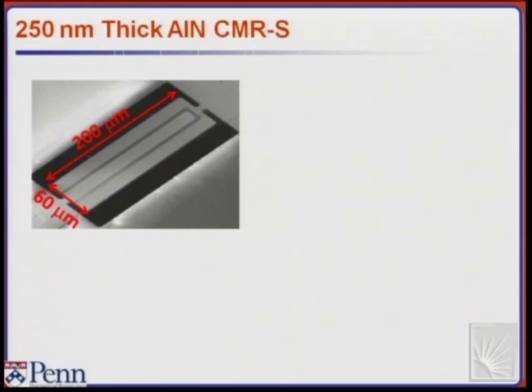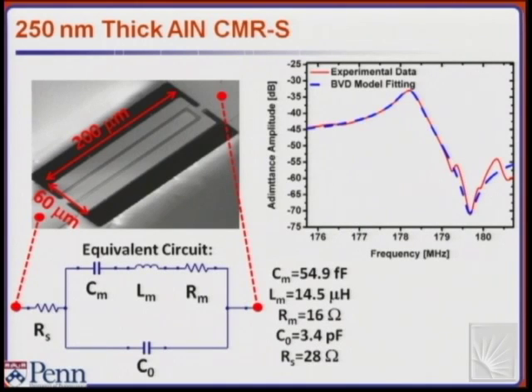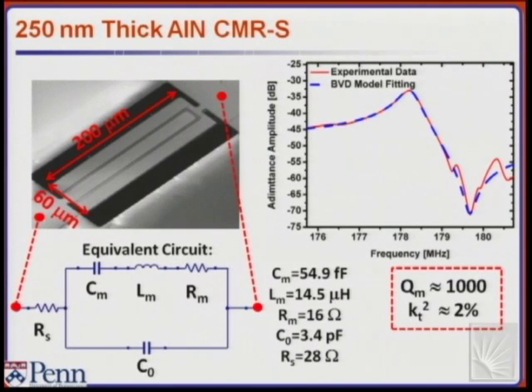So here's an example of a pretty big resonator that we made at the nanoscale. This was poorly designed because the 200 micron length is loading the Q, and I will show you experimentally that it's really loading the Q. But here's the mechanical response, and we can fit it with this circuit. Yes, the circuit is the same. The problem is this RS is pretty large. It's comparable to the RM, the mechanical impedance of the resonator. But the mechanical Q of the device, if you just look at the LCR, is still 1,000, and the electromechanical coupling is still the same.